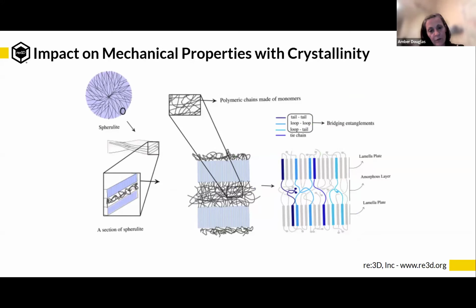Okay. So this is basically a diagram of the amorphous region would be in between these lamellae right here. The lamellae is when they kind of associate with their own self and they fold around, and then there's some of the amorphous part coming out. Polyethylene and polypropylene can have up to about 70% crystallinity sometimes. So that region can be pretty small, and you'd have a lot of those little spherulites right here. So if you're looking at it in a microscope, you would see just a bunch of those little circles right there. And you wouldn't know that if you zoomed in there, you'd see some amorphous in there too.